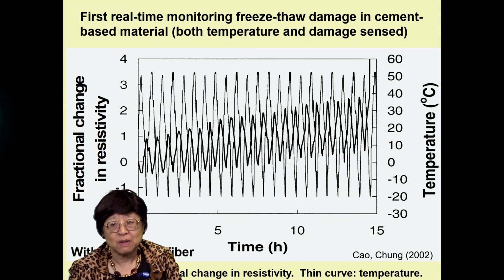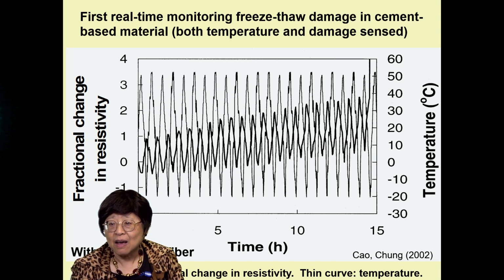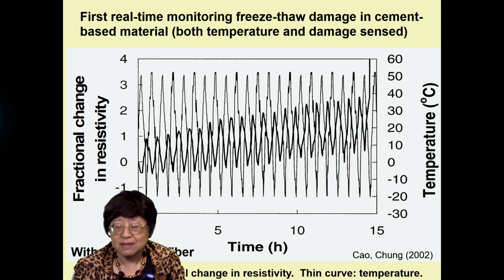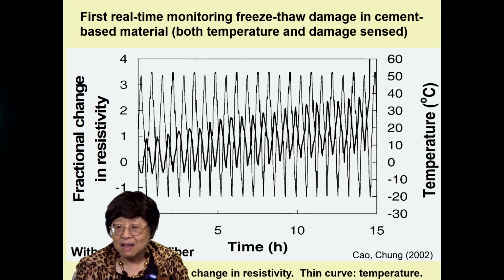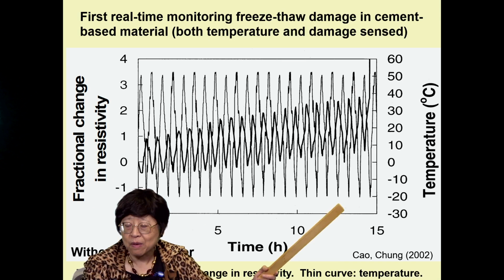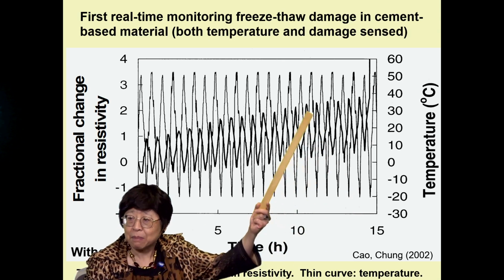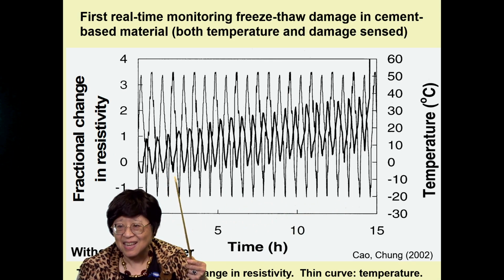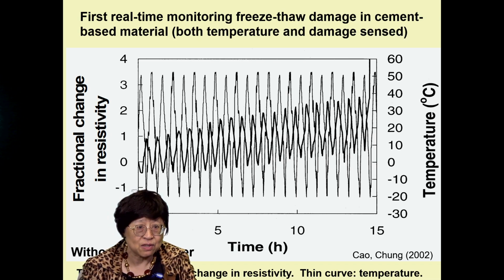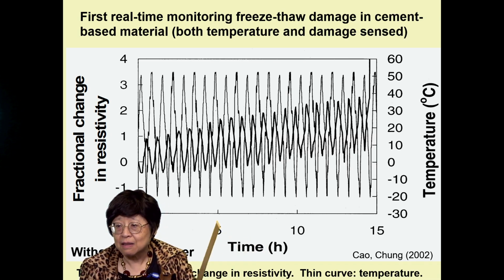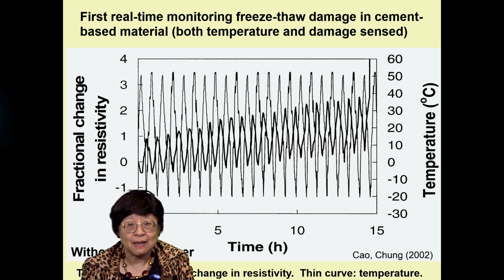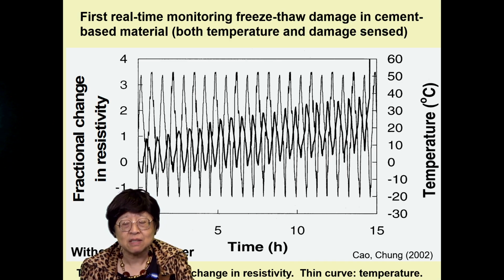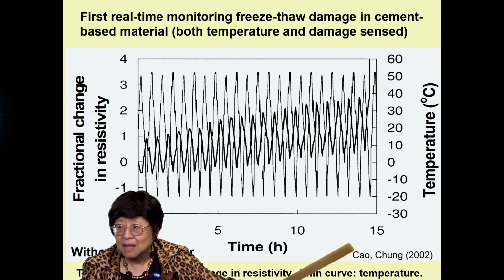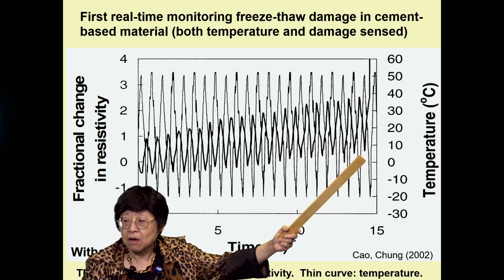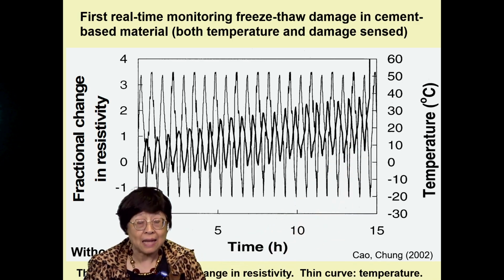By using resistance measurement during the freeze-thaw cycling, we are able to monitor the progress of this damage in real time. Shown in thin line is the temperature, going from below 0 degrees to above 0 degrees, quite a number of cycles. And in thick line is the resistance. You see that the resistance responds to every change in temperature. In addition, the baseline resistance climbs up steadily, cycle by cycle, meaning that the damage is incurred cycle by cycle until it fractures, and that last fracture occurs at the coolest point of the last cycle.